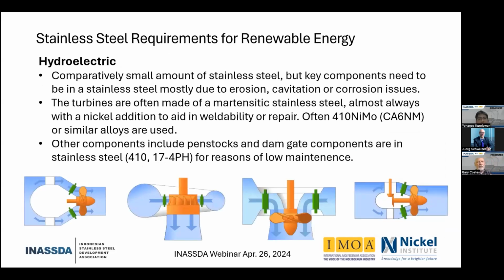So I'm going to just talk briefly about hydroelectric. That's certainly not a new technology. They use a relatively small amount of stainless steel, but the key components, again, will need to be a stainless steel due to the erosion coming from water at high velocity. Cavitation, that's where actually a little piece of the material pops off because of a very high velocity, or corrosion issues. Water is corrosive to a certain extent.